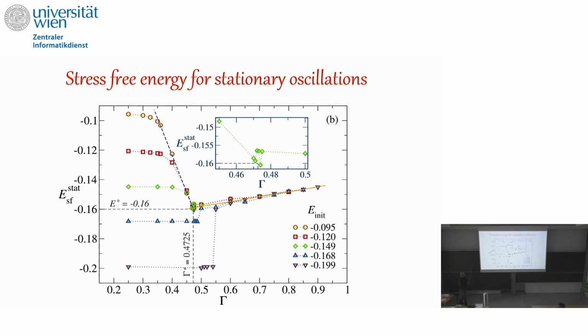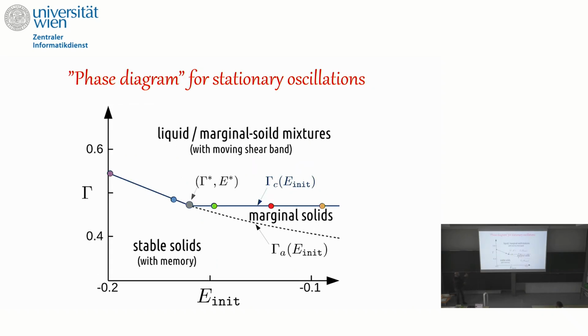Okay, so let's go on. The one important point I want to make is that now if you do many oscillations, you can look at the stress, you can look at the energy. And what you see is that if you take the ductile samples, the energy decreases with the amplitude until this critical point, which is 0.4725. And the energy of this sample is minus 0.16. So this point is a solid, and it's the last solid you can see with this oscillation. After that, you fail, and then the energy starts to increase. And if you prepare with an unbelievably good preparation, then you fail later, but then you follow again the same curve. So this is the phase diagram I want to show.